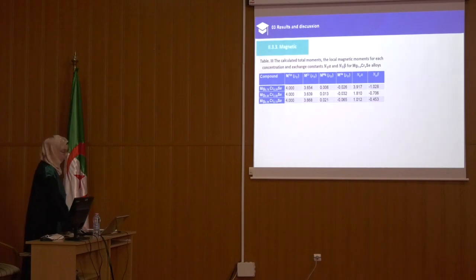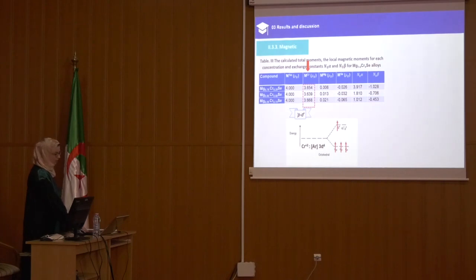For the magnetic properties, from the table we can see that the local magnetic moment of chromium impurity at different concentrations is smaller than the predicted Hund's rule value of 4, for the total magnetic moment, which is caused by the hybridization of the d states of chromium and the p states of Se. In addition, we see a small magnetic moment localized on the non-magnetic Mg and Se sites.